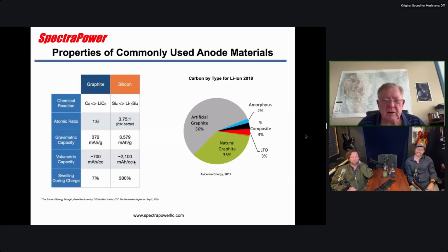So there's a lot of work going on. Right now what people do is mix in 5 to 10% silicon in the graphite. So a lot of the EV cells will have that. One advantage of silicon is its very high rate, especially on charge. So people will use it to speed up the charging. But they'll only mix in a small amount because it swells way too much. And then they don't fully lithiate it. So instead of 2100, you'll be down maybe half that or something. They don't use it at the full capacity.